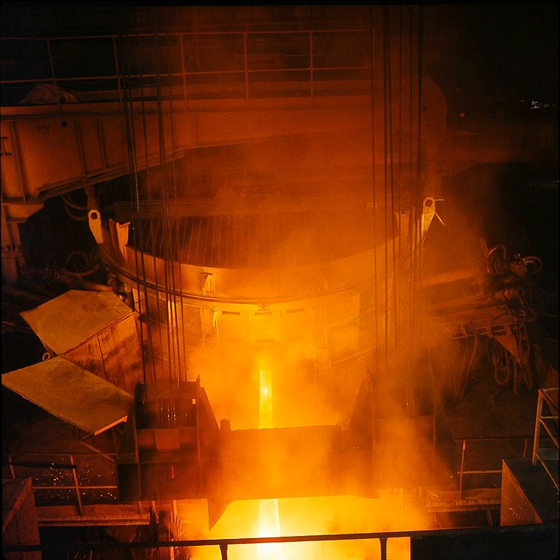The furnace is built on a tilting platform so that the liquid steel can be poured into another vessel for transport. The operation of tilting the furnace to pour molten steel is called tapping. Originally, all steelmaking furnaces had a tapping spout closed with refractory that washed out when the furnace was tilted, but often modern furnaces have an eccentric bottom tap hole (EBT) to reduce inclusion of nitrogen and slag in the liquid steel. These furnaces have a tap hole that passes vertically through the hearth and shell, and is set off center in the narrow nose of the egg-shaped hearth. It is filled with refractory sand, such as olivine, when it is closed off.